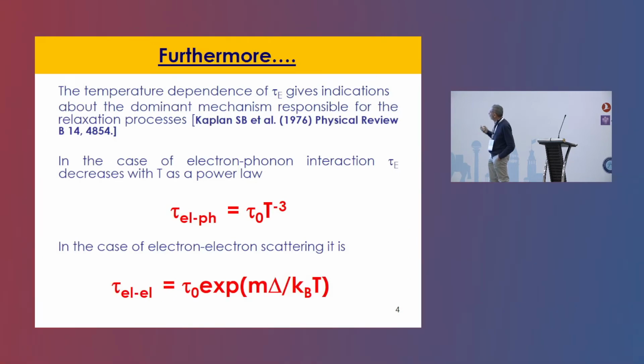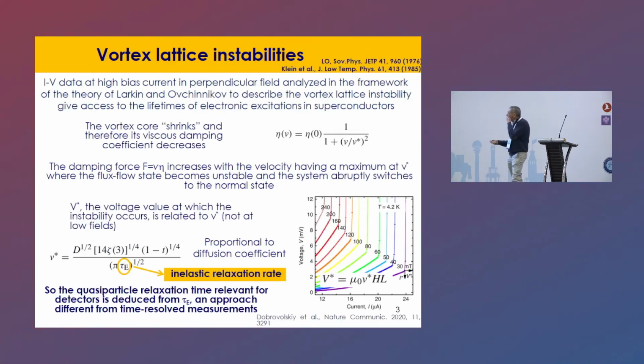From the study of the instability in the IV curves, we can have information about the critical velocity of the vortices, V star, which is related to this time tau e, the inelastic relaxation time of the quasiparticles. And from these numbers, we can make some prediction about the possibility to use materials as superconducting single photon detectors.